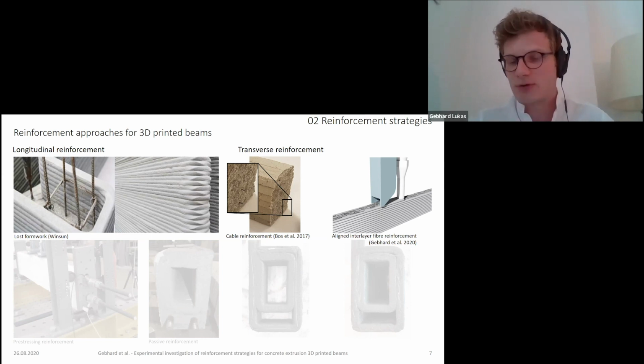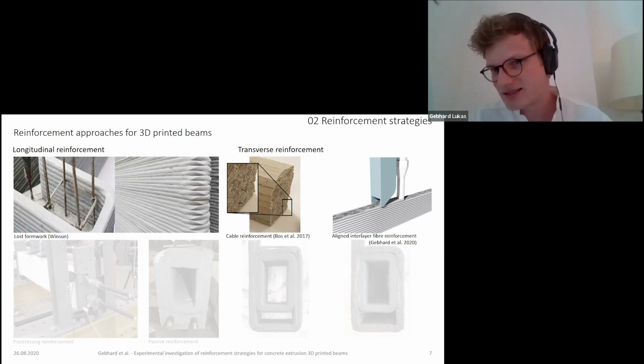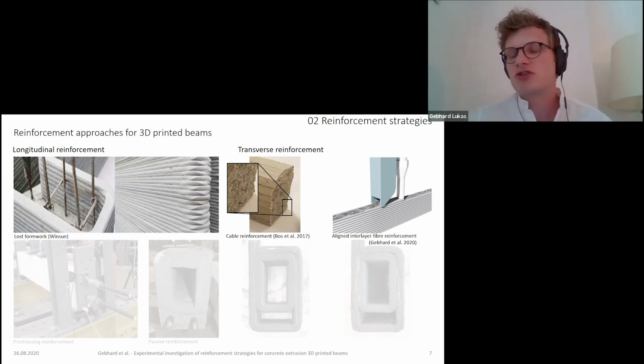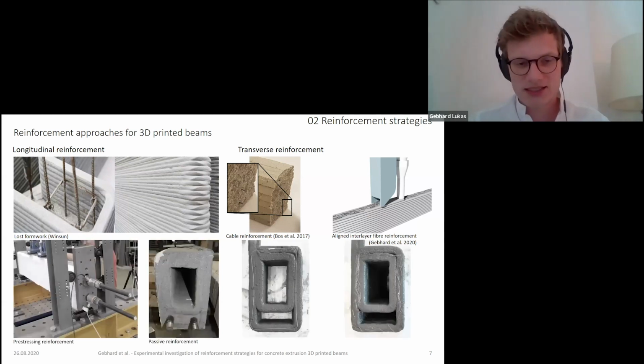And one approach was the cable reinforcement, which I already introduced. And the other one is a reinforcement strategy, which we have recently been developing, so-called aligned interlayer fiber reinforcement, where compared to the other fiber reinforced extrusion, we aim to not extrude the fibers and the concrete simultaneously, but rather extrude the concrete and place the fibers in the second step in between the layers. This allows the use of larger and less expensive fibers, and gives also flexibility in the amount of fibers that can be placed. And these ideas were then translated to a set of beams, which we tested in 4-point bending.